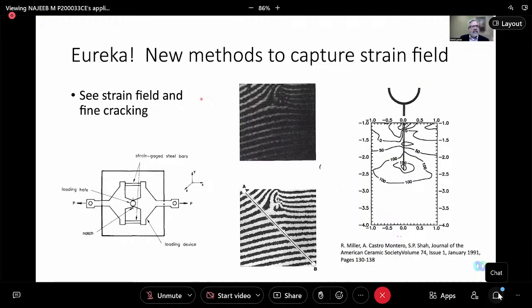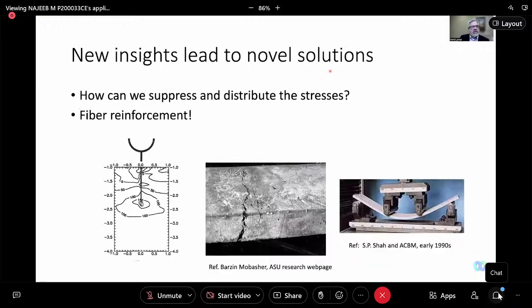And the eureka moments here are shown as, this is a holographic experiment by Rich Miller. And we've really had quite a few different people working in this field. So I think these techniques for measuring strains off of the surface were very important for understanding how cracks move, how they propagate, and being able to just simply visualize the fracture problem. And those insights, of course, lead you to think about novel solutions like fiber reinforcement. When we are understanding properly what's going on at the tip of the crack, ideas about reinforcing that come into play, and you can start to be able to measure and verify the benefits that you get from fiber reinforcement, the distribution of stresses at the tip of a crack.